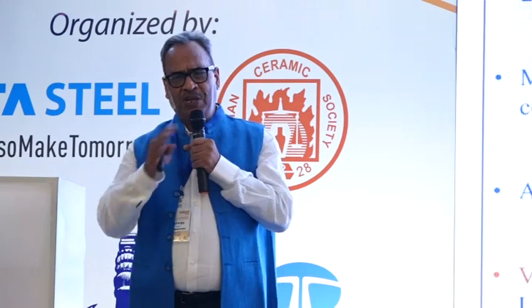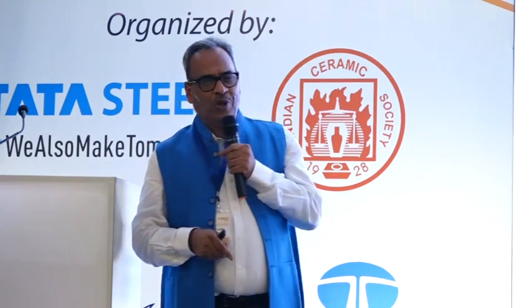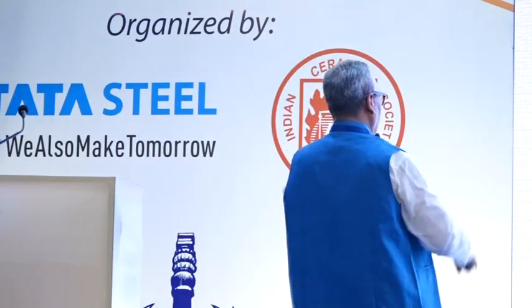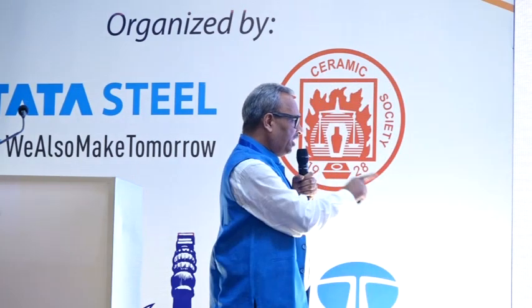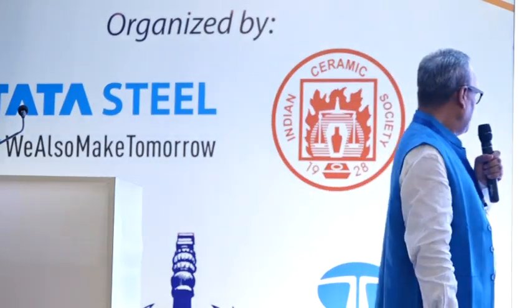Dimensional stability can be of three types. One is related with the alkali silica reaction. Another can be shrinkage, drying shrinkage, and all that. And the third type is the expansion. So the first kind, alkali silica reaction, was also studied. The volumetric expansion studies were done for evaluation of potential expansion due to the presence of free lime and magnesia in the LD slag as per a modified methodology.